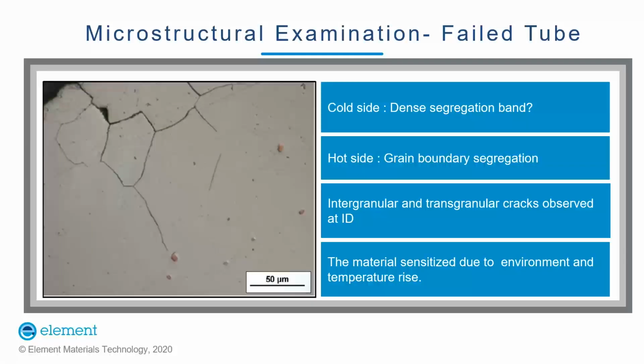Additionally, the microstructure at the crack location showed the crack appeared to have originated at the ID, the internal surface, at the hot side of the tube. The crack morphology appeared to be both transgranular and intergranular type, which is a very typical feature of a stress corrosion crack. It can be established from the above study that grain boundary segregation resulted in a sensitization of the tube at the hot side due to high temperature and environment condition.